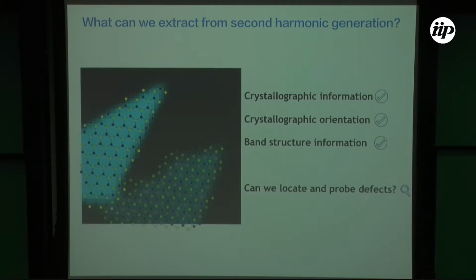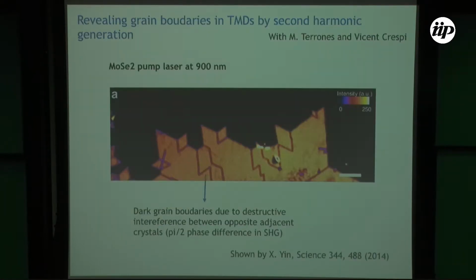And now another question arises: can we locate and probe defects in these TMDs by second harmonic generation? This work was mainly done by Bruno here from Natal, and for this work we have used MoSe2 samples. These are CVD samples, and you see that the CVD samples are quite large, and the second harmonic emission is very homogeneous. But then you see some dark lines, very straight dark lines around the flake.